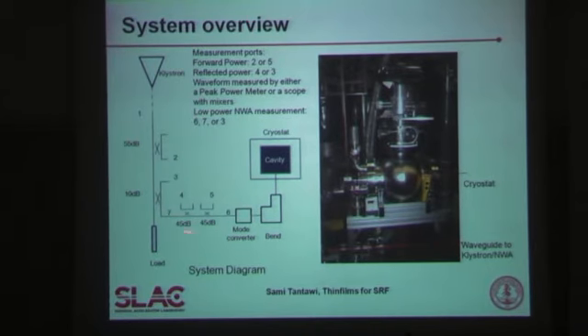Furthermore, in situ, we can turn off the klystron, attach a network analyzer here, and then characterize the cavity at low power and understand the Q. And it turns out that we can do a reasonable job in measuring the residual surface resistance. This is an added bonus. We didn't realize that we could do that because we thought that this would be completely dominated by copper. But it turns out that we can really, with a small variation, understand the residual surface resistance, especially when it became very high when we did this experiment.